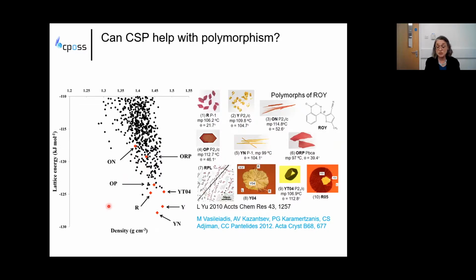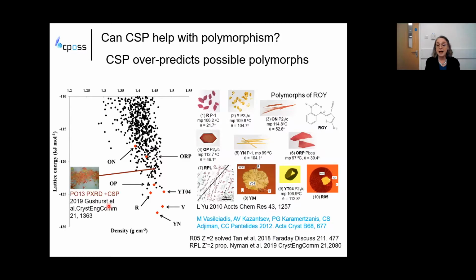Now, this was a search with just one conformation of the molecule. And after this search, other people found and used crystal structure prediction to solve the structure of two of these polymorphs, which happened to be not on this search because they had two different conformations of the molecule. And in 2013, there was a pumpkin orange polymorph observed, but hopefully you can see that there's sort of yellow crystals mixed in with it, which made it impossible to solve from powder this structure. But in 2019, this crystal structure prediction was used to solve the structure, and it was one of these points here.